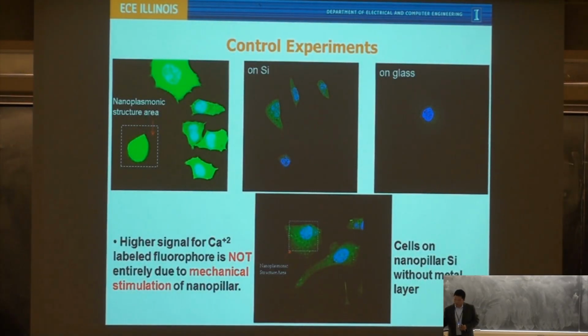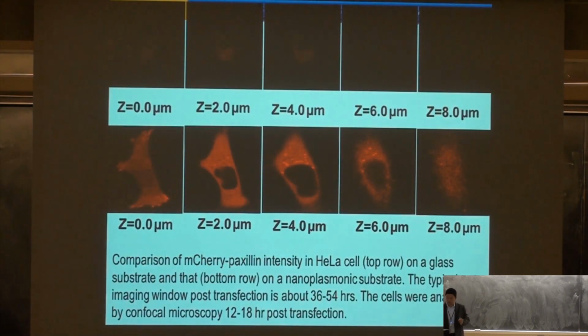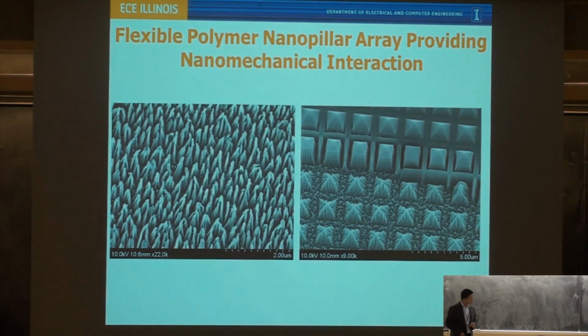We actually did a lot of cell growth studies on nanostructures, especially on these silicon nanopillar structures. So that triggered us to think, is there any nanomechanical interaction between the cells and the nanopillar, especially when the nanopillar becomes very small, very high aspect ratio, and very flexible? So what we are doing now is trying to create high-density nanopillar polymer. You can see a lot of high aspect ratio polymer nanopillars, which are really flexible.